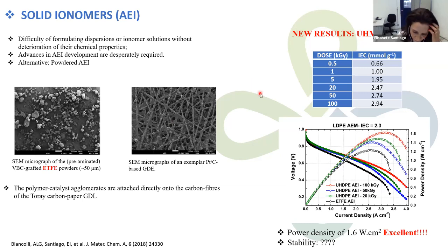So searching for performance stability, ultra-high molecular weight polyethylene powders have been synthesized, and the preliminary results showed a broad range of IEC depending on the EB dose rate. It's fine to reduce the conductivity and water absorption capacity to obtain performance stability.